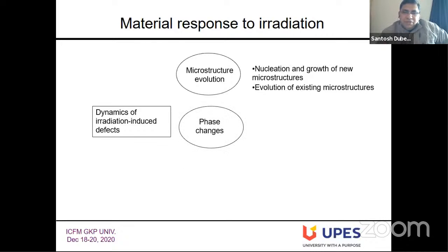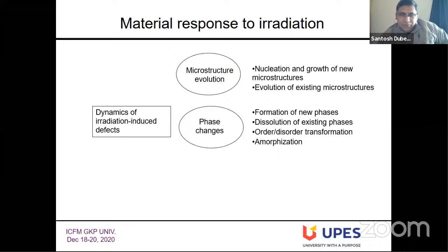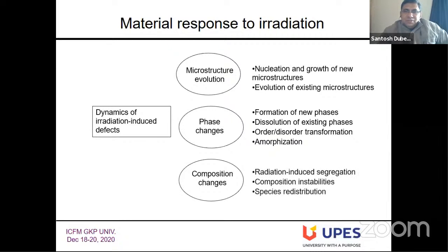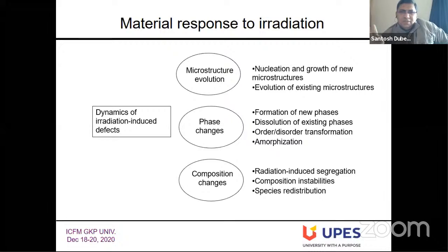Because of irradiation, you may have phase changes, like some phase was there, and after irradiation that phase evolved in some way, like formation of new phases, dissolution of existing phases, order-disorder transformation. You may also have amorphization and so on. Or you can have just compositional changes. Compositional changes may include radiation-induced segregation, compositional instabilities which may be spinodal type instabilities, or compositional changes which may not lead to phase separation. Or you can have just the smallest thing, species redistribution, which doesn't lead to any big observation like the formation of a new phase. That depends on the level of radiation the material is having.